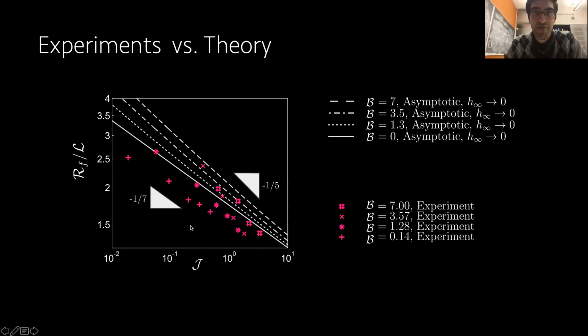Let's go through it in a little more detail. The very good thing that made me happy is that the scalings look pretty okay when you compare with the experiment. If you look at the crosses, this is my smallest Bond number, so my scaling of -1/7 should be valid, and it's fairly there. It looks like the experiments are moving towards the gravitational dominance scaling when the droplet becomes large. It also looks like my asymptotic solutions are systematically overestimating the experimental results. And there is also some behavior at large J values that doesn't follow a simple scaling.